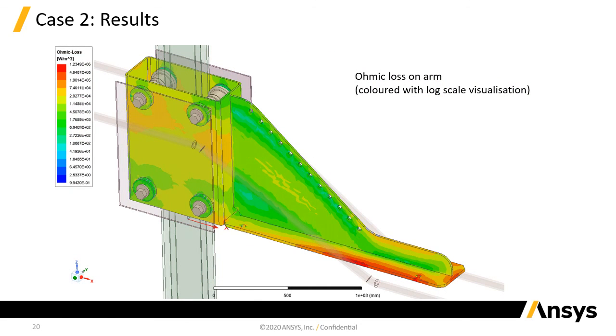All right, and if we look at the ohmic loss within the mast or the arm, you'll see here that in the area where the bus tube runs close to the carriage, we get quite a significant reduction in the overall ohmic loss in that area. But if we look down at the end of the arm, where there is no shielding and where the bus tubes run close to the arm there, we still get a similar loss as before. Okay, so we can see that there's a very localized effect from the shielding. So that's something we really need to take into account moving forward with this design.